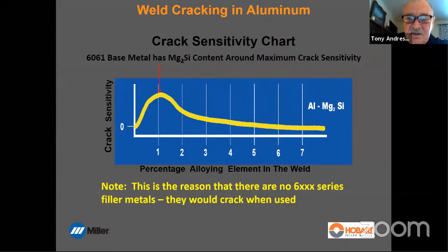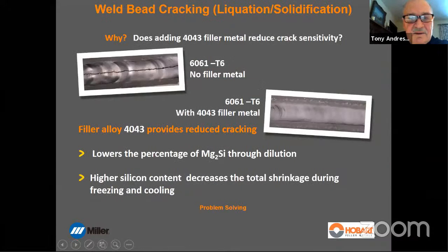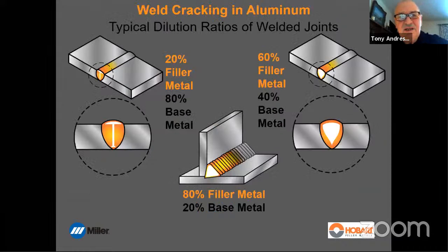This is the reason there is no 6000 series filler alloys. If we had a 6061 filler alloy, every time we used it, it would crack. So why does it not crack when we had the 4043? Well, as I said, we changed the chemistry, and we also have high silicon, which I told you earlier reduces the shrinkage during the freezing. So 4000 series is very good to prevent cracking.